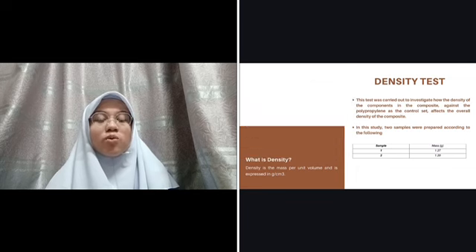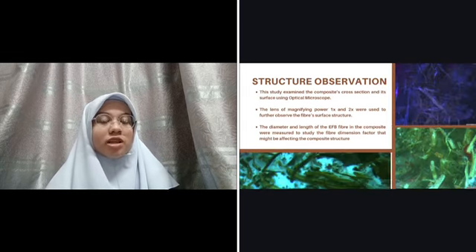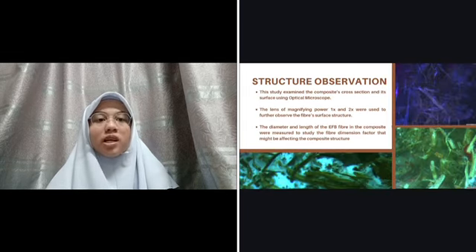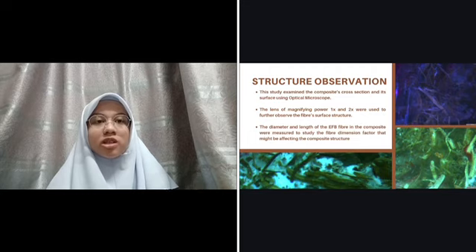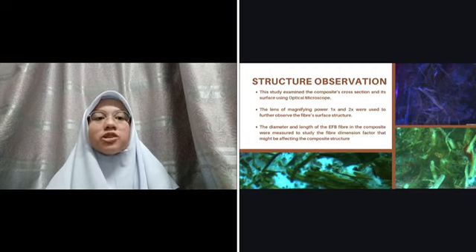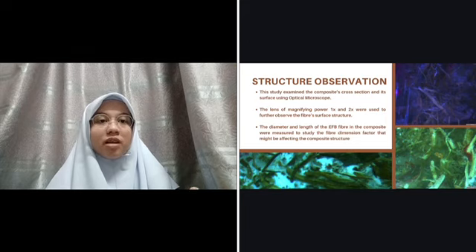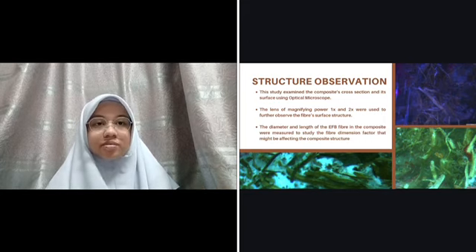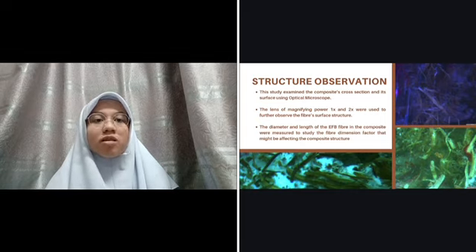And lastly, we observed the surface structure of our composite panel using an optical microscope. This study was conducted to examine the composite's cross-section and its surface. In this test, we measured the diameter and the length of the fiber so that we can study the dimension factor of the fiber that might affect the composite structure. And that's all for Chapter 3.